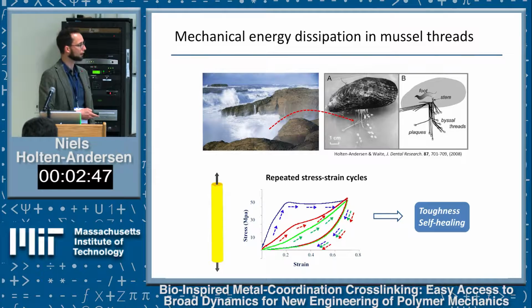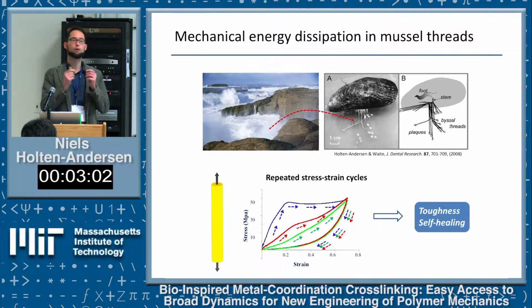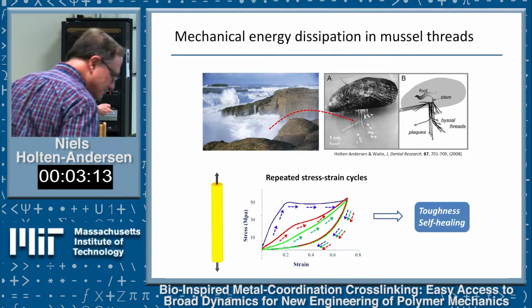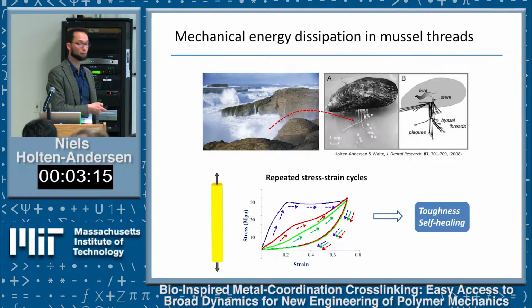If you take one of these fibers and pull on it three times in a row, what's impressive is that the first time, you see an initial very stiff mechanical response that then suddenly breaks over into what we call the yield point. Then you can keep pulling the fiber out into a very long stretch without it actually breaking. If you let go, the fiber will slowly go back to its resting length, and the area inside this loop is what we call the dissipated energy.